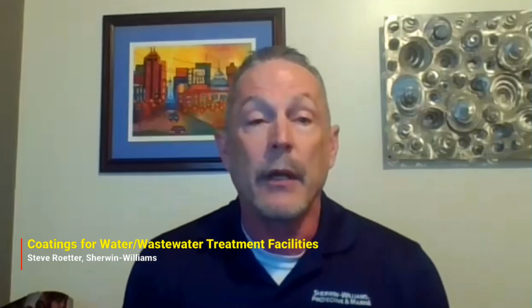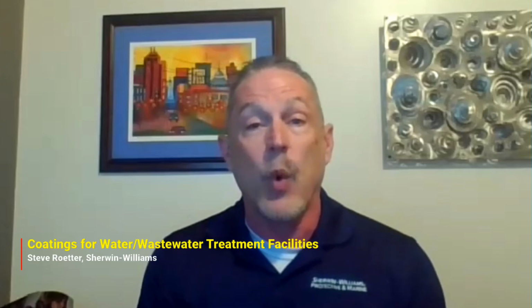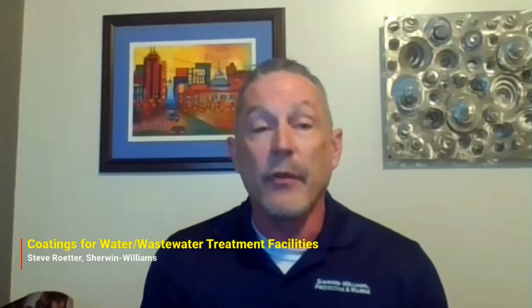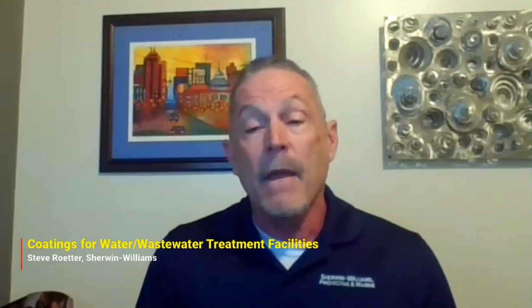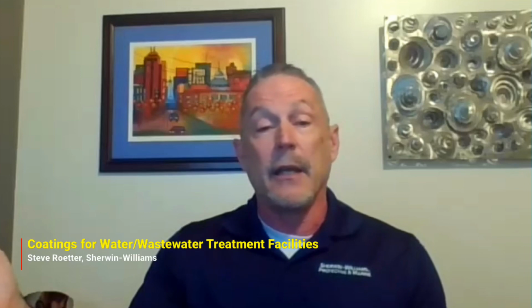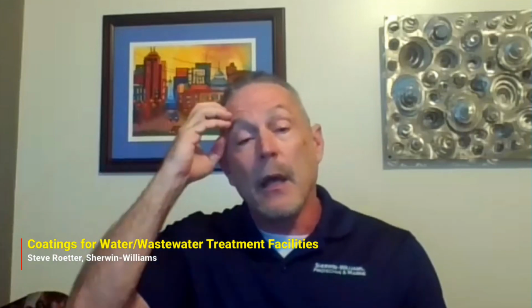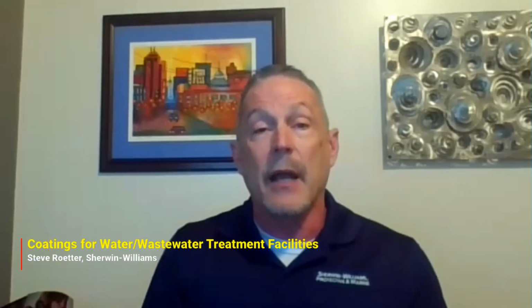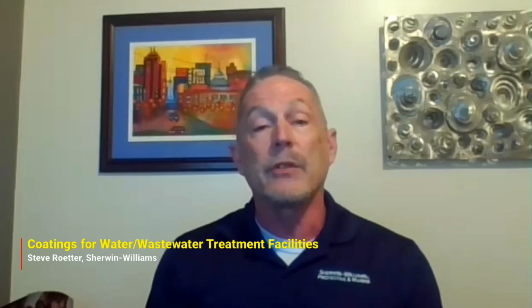He was also instrumental in helping to develop what's called the Severe Wastewater Analysis Test, or the SWAT test. And it's now ASTM G210. This is an accelerated testing protocol to qualify coatings for long-term severe wastewater services. And, that said, I still see a lot of owners specifying older technology. Probably one or two a week. I try to convince them not to specify coal tar epoxy, for instance, which is an older technology, and it's just not up to the conditions that we're seeing today.